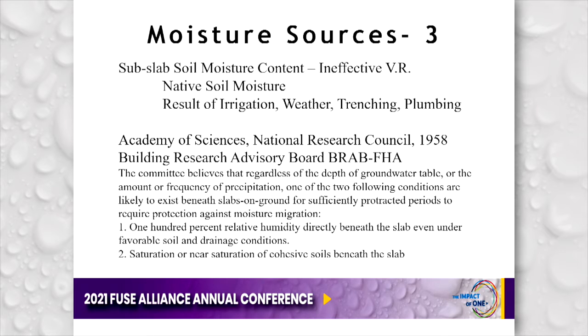The third place we need to look is the native subslab soil moisture content. And here's where an ineffective vapor retarder becomes a real problem. This is the native soil moisture, but it could be the result of irrigation, weather, trenching, plumbing. And we have data going all the way back to 1958, when the Academy of Sciences for the FHA studied soil under concrete floor slabs, and they found that regardless of the depth of the groundwater table, 100% relative humidity directly beneath the slab was typically going to be found in soil, even under favorable drainage conditions. So I'm here to promise you that if the soil can reach 100%, the slab can reach 100%. And that's where a lot of our problems come from.